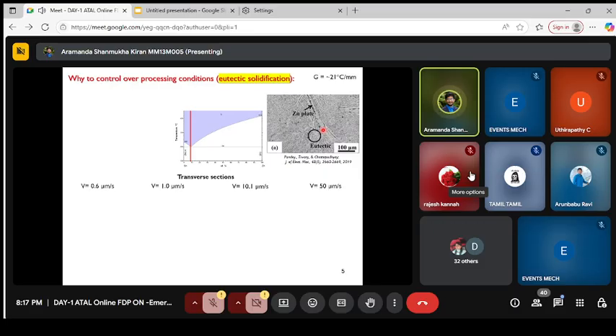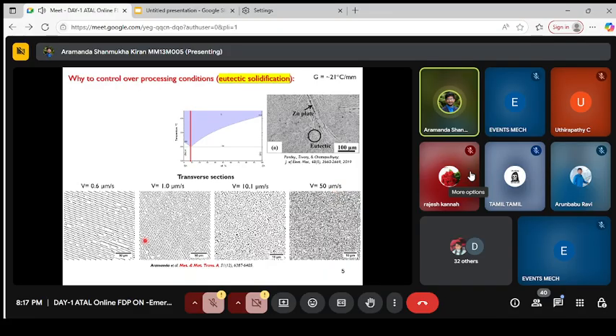So again, here also, when we do a very controlled experiment with a very slow velocity, 0.6 micron per second to 50 micron per second, what we can see, this white thing is tin, black thing is zinc. So we can see how well they are organized. They are formed periodically. So we can get some structure like that with a very controlled experiment.